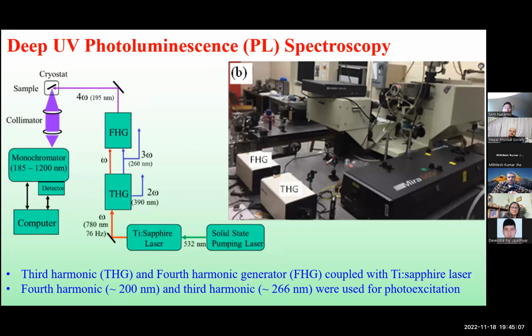All right, for this material, we use photoluminescence spectroscopy to study the optical properties. In our system, we have a Ti sapphire laser. The Ti sapphire laser is pumped by a solid state green pumping laser, and it gives a pulsed laser. The pulse width is about 100 femtoseconds, and its repetition rate is 76 megahertz. So it's a stream of very short pulses of 100 femtoseconds, and then another pulse comes only after around 13 nanoseconds.